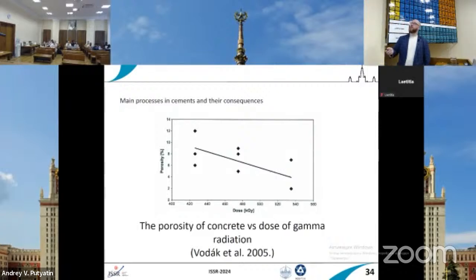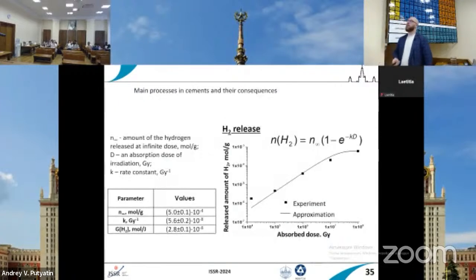Also, we can see, although it's very scarce data, that the porosity of the cement materials is decreasing with the gamma radiation, and the decrease in porosity means that the material becomes more dense and more durable. The production of hydrogen, as I mentioned on Tuesday, is limited. Also, that means that we can use these materials maybe even for some sort of high-level waste.